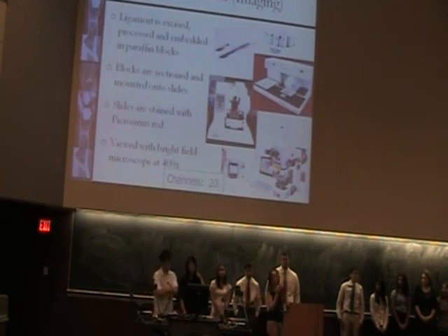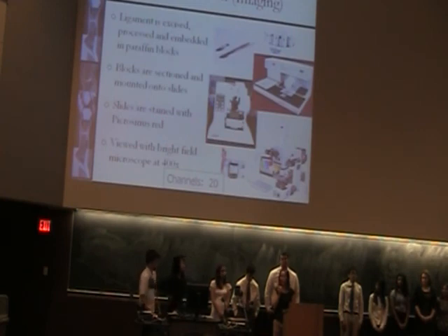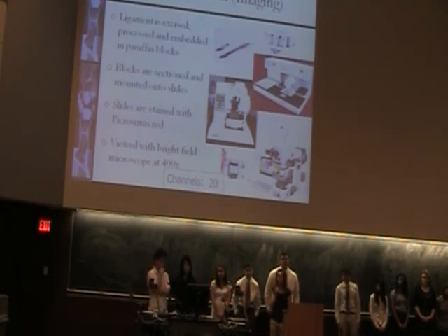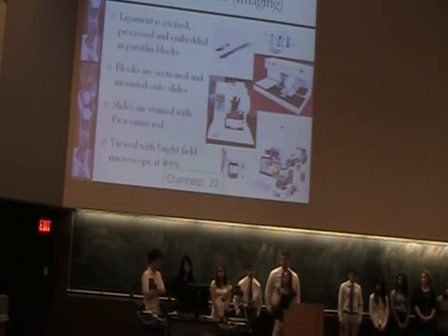Okay, so this semester we worked on our imaging method and analyzing and imaging our tissues. It requires multiple steps. We first excise the ligaments and we process and embed in the tissue processor. And we take blocks of paraffin, section them, and we use the microtome to prepare our slides. We then stain the slides and capture images digitally using polarized light microscopy.